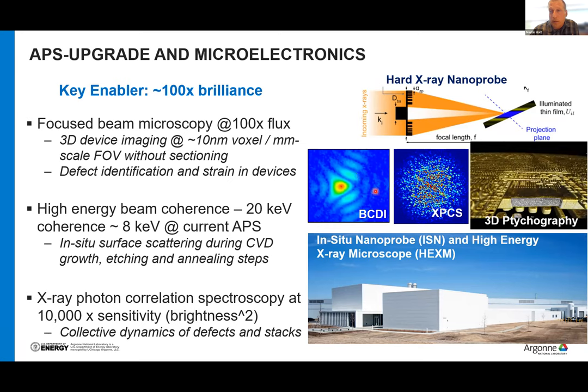Bragg coherent diffraction imaging, of course, relies on the coherent fraction of the beam. Photon correlation spectroscopy, actually, because that uses the correlation of two different measurements above Poisson statistics. The fidelity of that goes up as the brightness squared. So it could potentially be 10,000 times better. And as Dylan was speaking to, give you enough of a momentum space view to get down to the atomistic level of fluctuations on this sort of microsecond to millisecond to second time scale.